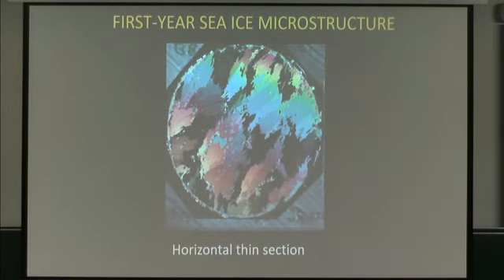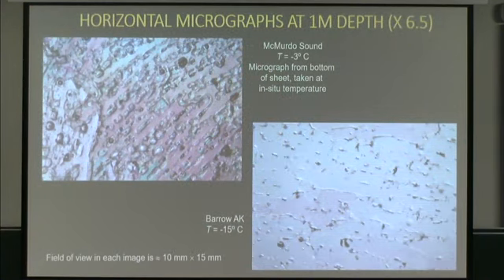So we can put this ice under cross polarizers. Because of the birefringence, this shows us individual grains. And so these are the guys we can study and get orientations of these crystals that help inform the model. So when you see that omega parameter, that is the result of computations that have to do with how these grains are all oriented relative to each other and relative to your stress direction.